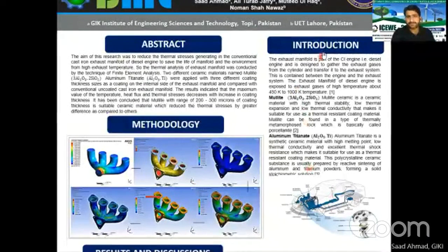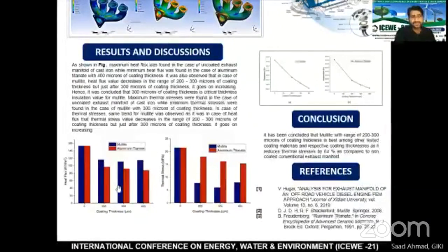So we concluded that in the case of mullite, with coating thickness up to a range of 200 to 300 microns, the thermal stress is reduced by 64% as compared to the conventional cast iron exhaust manifold, while the heat flux increased by a little amount as compared to aluminum titanate, but it was also fruitful in terms of saving the manifold from corrosion as well. We also got good results in terms of temperature in the case of mullite, but after 300 microns of coating thickness, the heat flux and thermal stress go on increasing, so we found that it was the critical thickness.